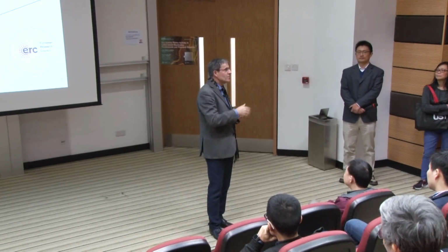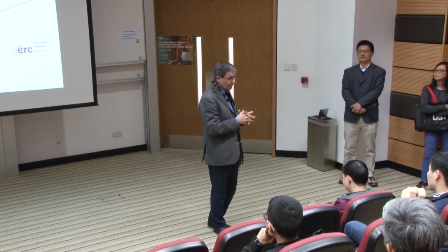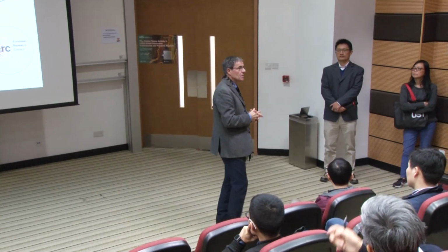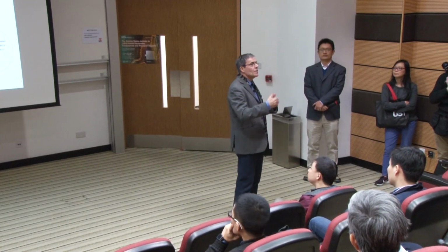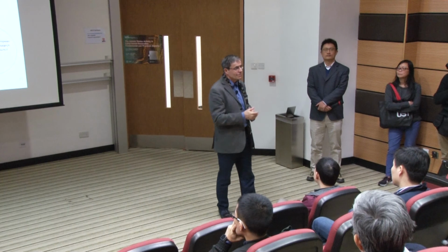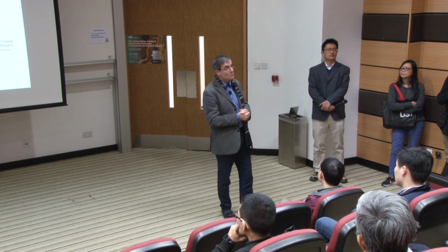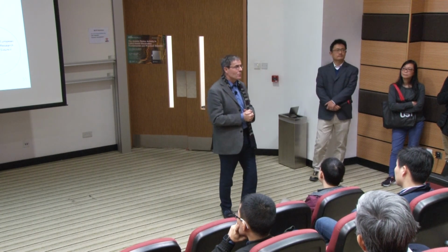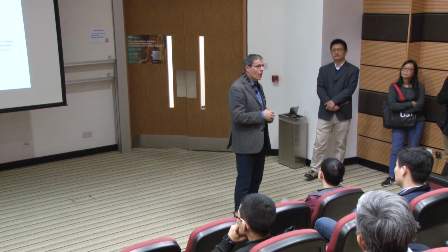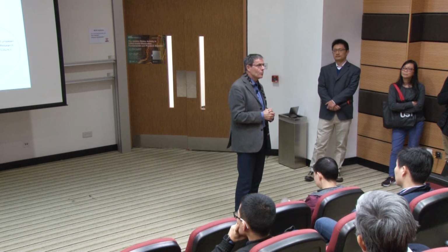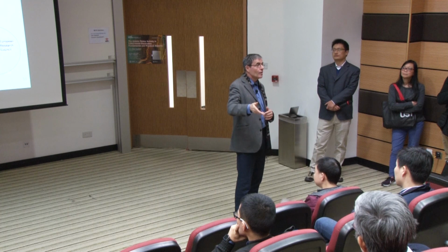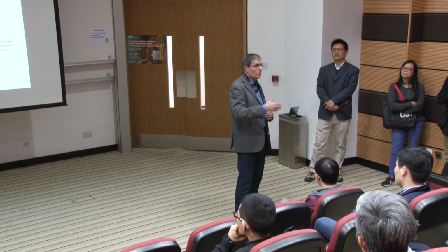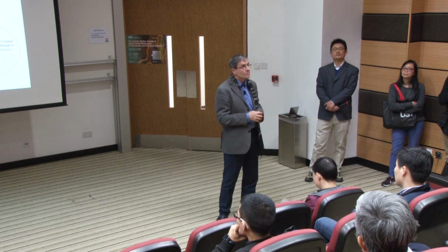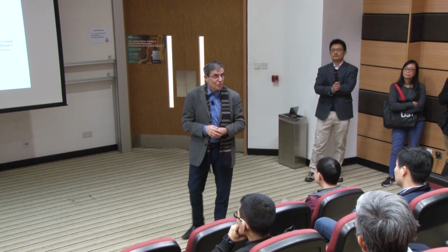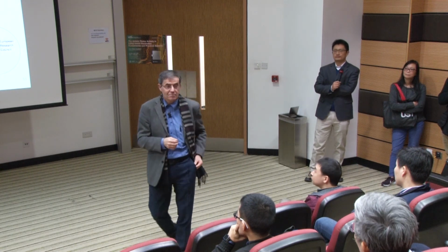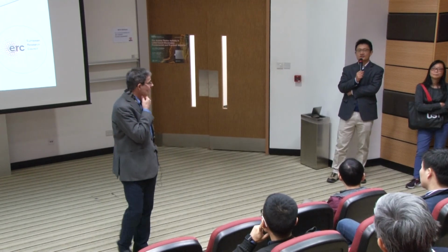So of course, when we found this stuff, we said, great, we solved the issue. And we went back to lithium-rich NMC. And we tried in this case to substitute with tin. Unfortunately, we couldn't make the phase. We were able to substitute, like manganese 0.27, tin 0.25. We could never replace manganese fully by tin. But it was more or less what we have been trying, and we failed. Yeah, let's have one last question.